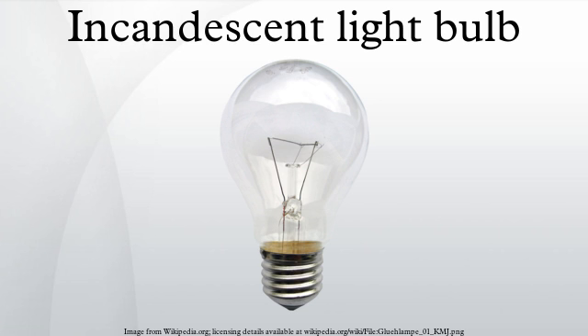To improve the efficiency of the lamp, the filament usually consists of coils of coiled fine wire, also known as a coiled coil. For a 60-watt 120-volt lamp, the uncoiled length of the tungsten filament is usually 22.8 inches, and the filament diameter is 0.0018 inches. The advantage of the coiled coil is that evaporation of the tungsten filament is at the rate of a tungsten cylinder having a diameter equal to that of the coiled coil. The coiled coil filament evaporates more slowly than a straight filament of the same surface area and light emitting power.